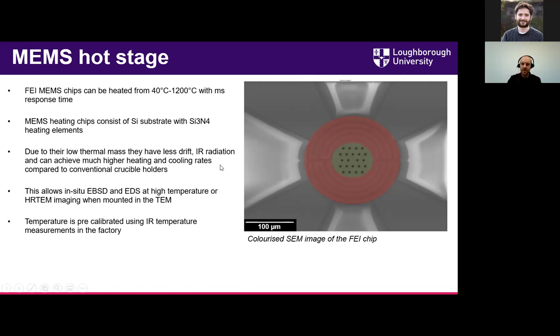One of the concerns people often have with these MEMS hot stages is that they are pre-calibrated using infrared thermal measurement inside the factory. So you're just given a correction value, and then you're measuring the resistance across this chip to determine temperature. You're not physically measuring the actual temperature with a thermocouple, you're inferring it based on a measurement done at the factory. And this can lead to some concern sometimes by reviewers. They're not always sure that they believe those values and that kind of thing.